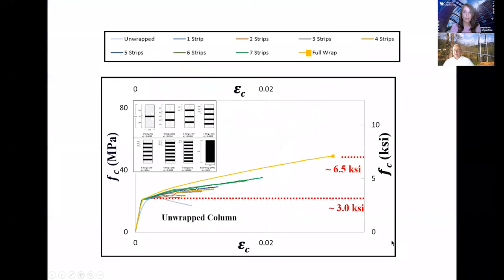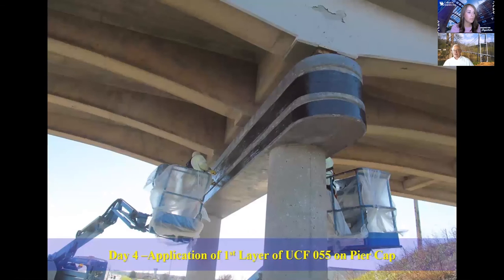So what we do, we know from all our lab and theoretical analyses that if you confine concrete, this would be the original strength of the concrete when it's not confined. When we confine it, depending on how much fabric I put on it, I can increase its capacity to be more than double its original, just because I confined it and I'm not allowing it to expand in this circular shape. So this is the approach that we take when we are strengthening these pier caps in there.